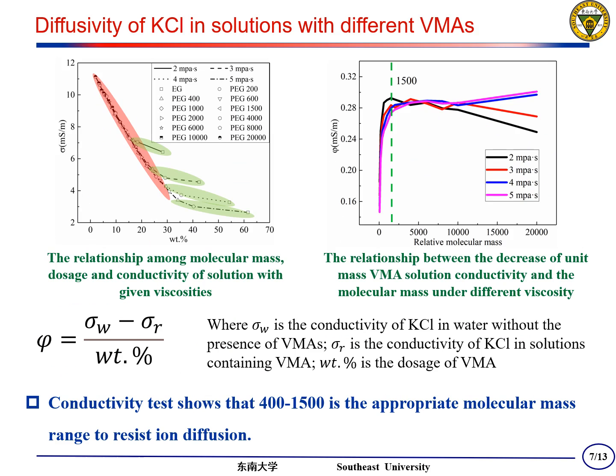Through the further analysis of the previous two figures, we found that the slope of the part covered by the green shading is much smaller than that of the red shading, demonstrating a decline in efficiency in reducing the conductivity. Therefore, the turning point molecular mass 400 is regarded as the lower limit.